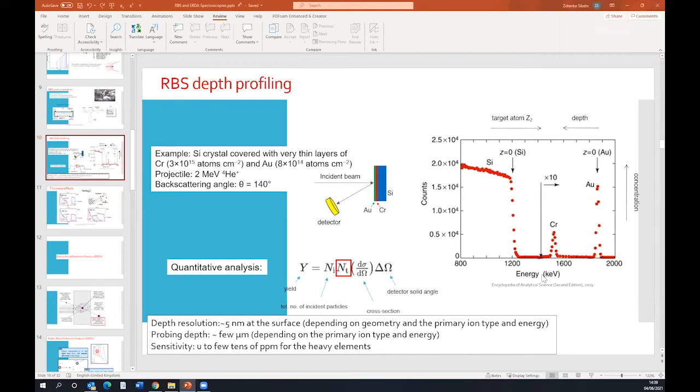That could also happen if laterally you have some islands of the material, not uniform, and then the spectra looks different. And if you don't have any information from AFM or from electron microscope, then you can draw wrong conclusions about your sample.